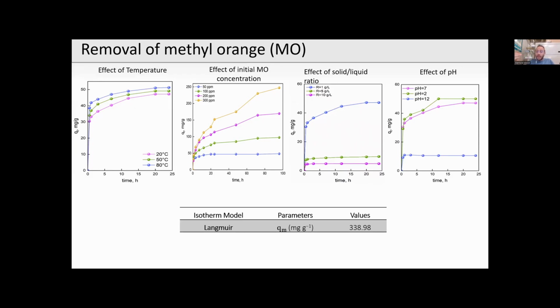While as the pH increases, the surface of the sorbent is supposed to be negatively charged and the methyl orange is supposed to be in its anionic form. Moreover, at a really high pH, the double bond nitrogen of the methyl orange ion is supposed to be strengthened. So the diffusion and the movement of this molecule is limited, justifying the experimental adsorption data.